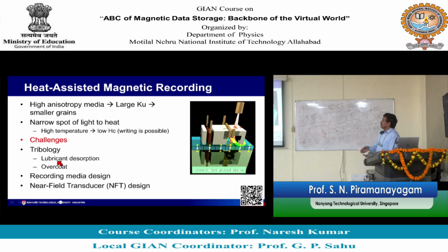So, you know that if you have polymer, you heat at 400 degree, it will not be stable. Okay, so the lubricant will be gone, and when you heat the carbon overcoat at this temperature, carbon overcoat will be spoiled, and so on. So there are many such problems. So recording media design also is a challenge. You need to make the sample withstand high temperature. Again, so far, we have very well established how to grow perpendicular media with isolated grains. So all those things we need to do all over again. So how to make the iron platinum grains to be separated from each other. So all those recording media principles have to be redone all over, start from scratch, do many things.